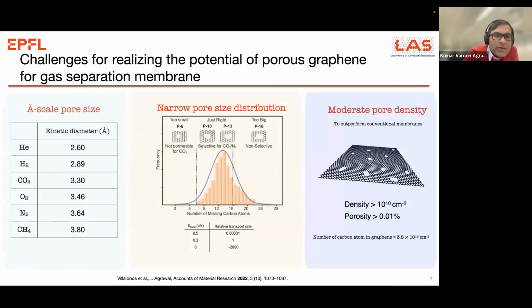And not just any hole. The holes have to be of a particular size and have a few characteristics. Here I define 3 different characteristics. The first challenge is that you have to have a hole of the size of the gases. Now, how big are the gases? Here are some of the light gases. CO2 is here, 3.3 angstrom. The other gas that we want to separate is nitrogen, the predominant gas in your flue gas. The size of CO2 is 3.3, nitrogen is 3.64. So you have to prepare a pore which is angstrom size, but not bigger than 3.64 angstrom.